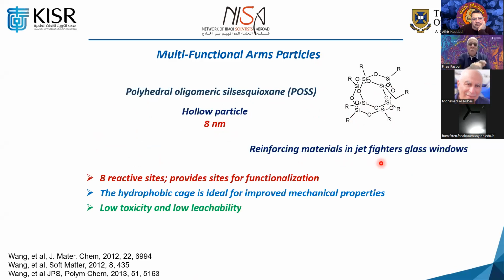They usually put a polyurethane sandwich between two glass panels to make the glass bulletproof. So they use this compound with polyurethane as a reinforcer in order to prevent the shattering of the windscreen in jet fighters and any airplanes. So this is really one of its applications.